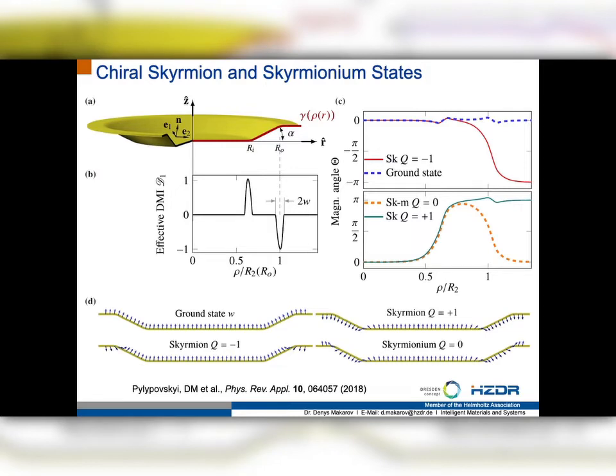And what is important, now you can manipulate the size of this Skyrmion not by the intrinsic properties of the thin film which you use for this investigation, but by the geometry. So you can make a smaller Skyrmion, you can make a larger radius Skyrmion simply by playing with the radius of these band regions in the system.